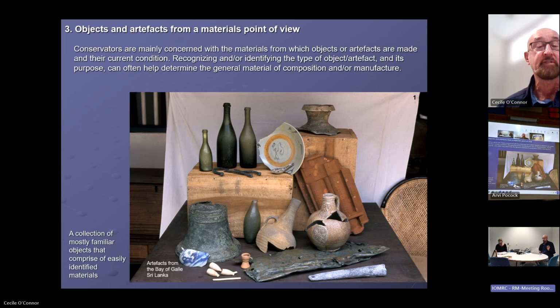So there is a possibility you could recover it and dry it and it wouldn't have an issue, but it's always safer to desalinate. And desalination takes place initially, usually for ceramics, we recommend you use seawater with half fresh water, so you're not giving it osmotic shock. If you've got a strong solution in the object and a weak solution outside, if the salt's trying to come out too quickly, it can possibly damage the surface. Can't say I've ever seen it being a problem, but that's what we're supposed to do.